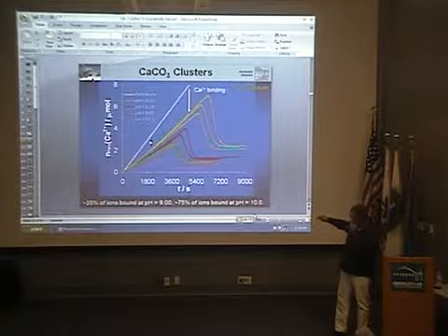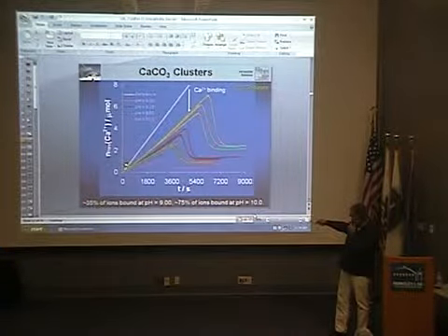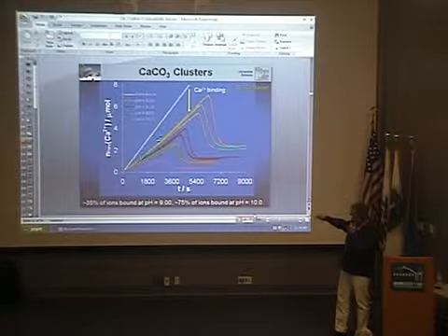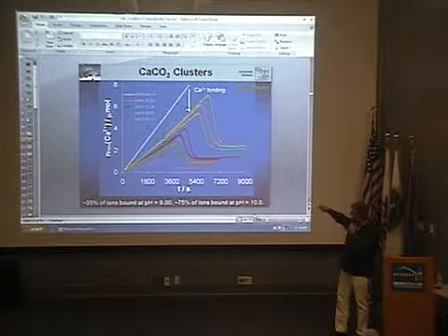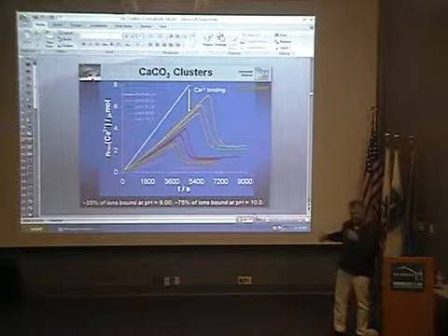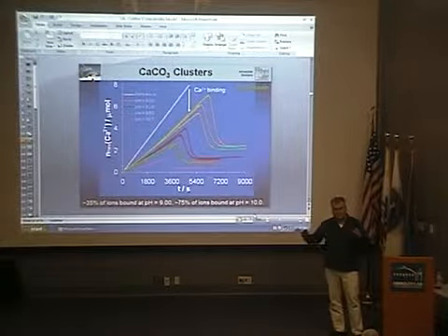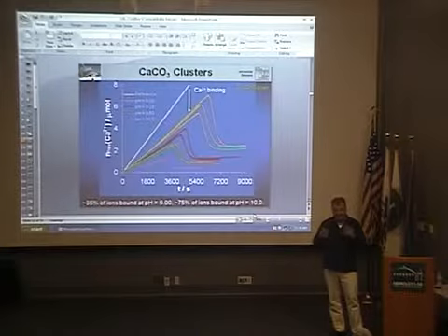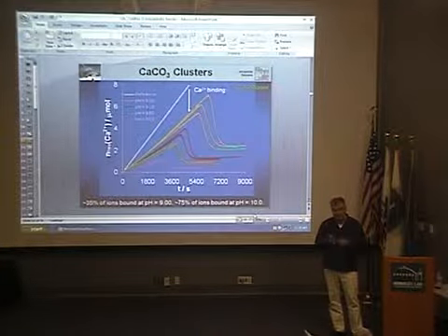And I deduce this from the fact that the calcium concentration or activity is still increasing if I add calcium, whereas here in the two-phase system, after nucleation, where I have particles, it remains constant. That means the clusters are soluble before, so they shouldn't have any interfacial energy.